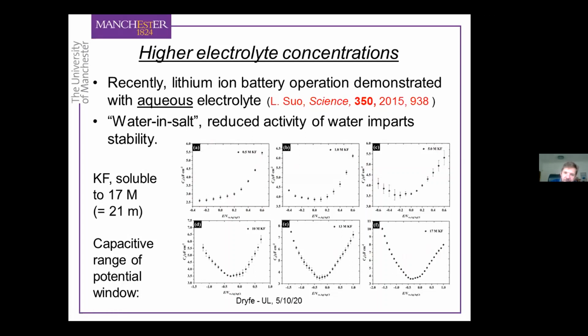If you look at the capacitance values, they don't change too much. We're typically in the range of 5 microfarads here. We go up to like 10 microfarads per square centimeter here. So the capacitance doesn't change too much. But the thing that does change enormously is the potential range, because we're only recording the capacitance over regions where the impedance response looks purely capacitive. So at the low concentrations, that's only over about 1 volt.